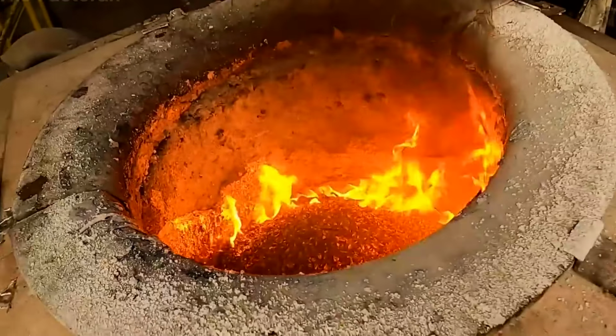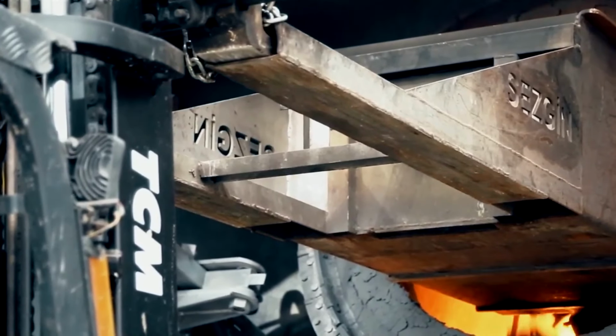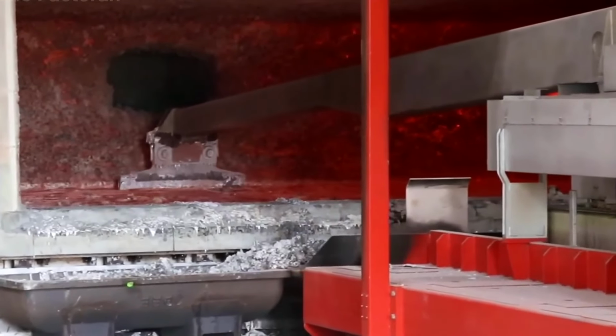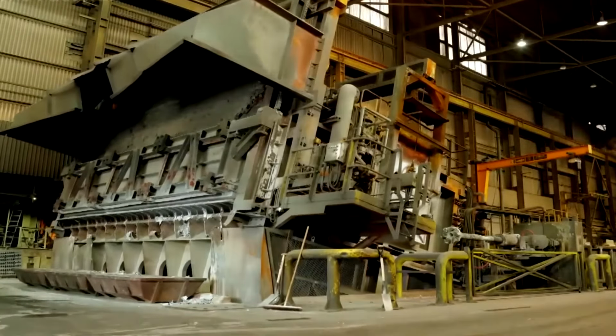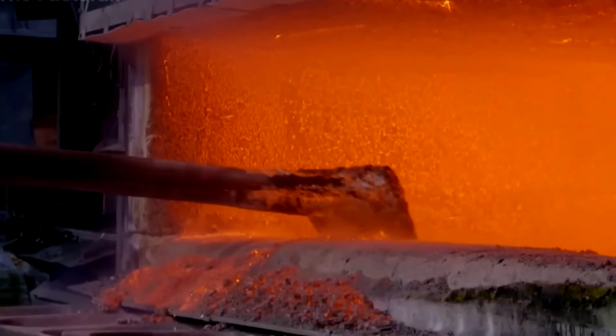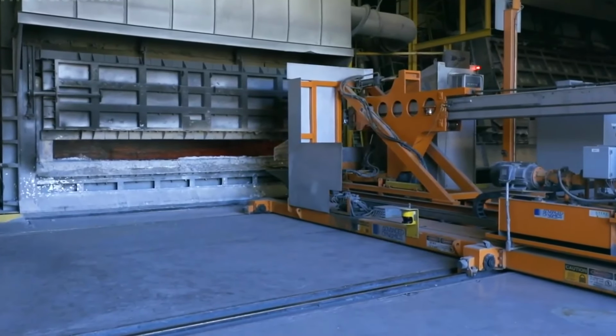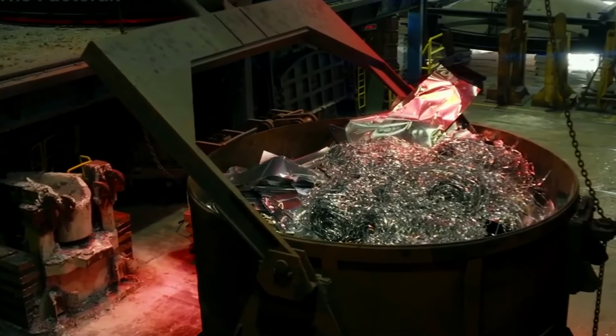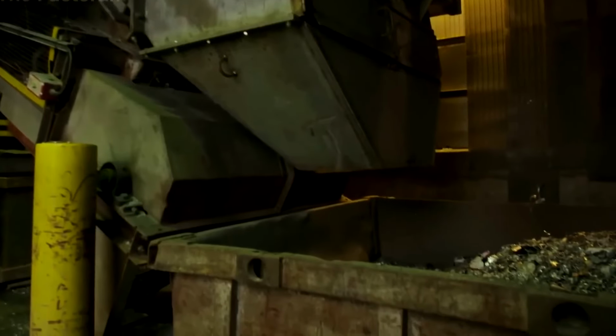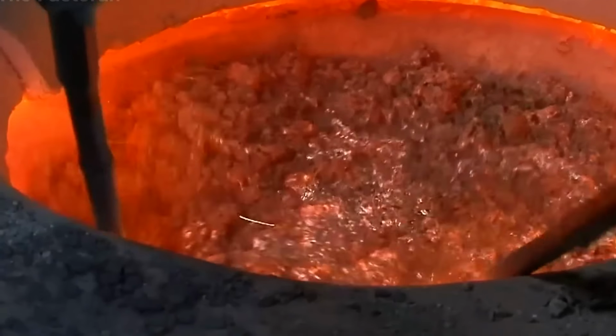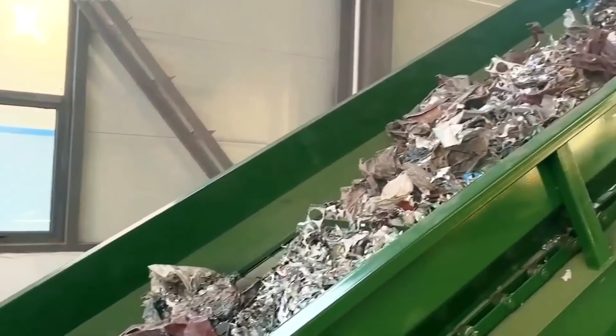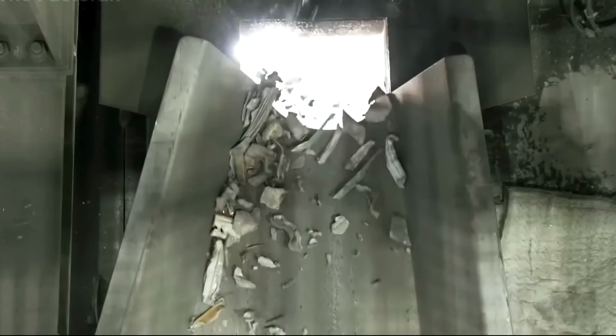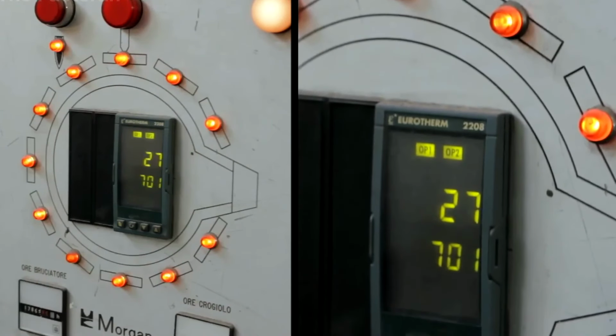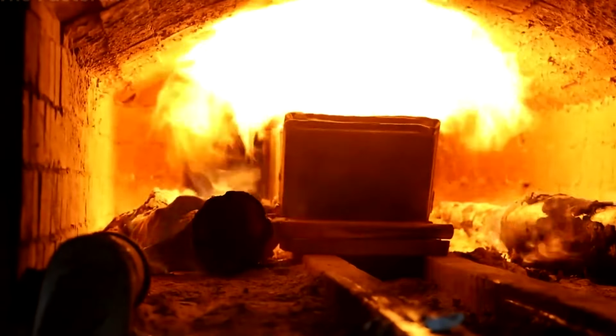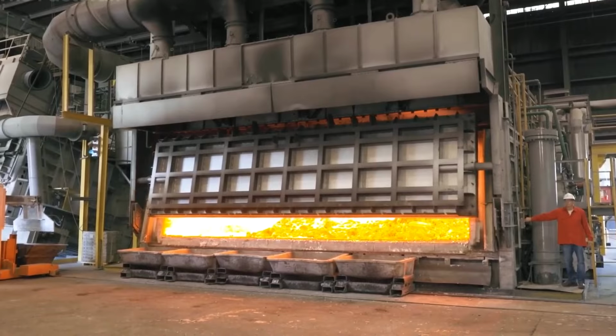Even after the aluminum has completely liquefied, it still harbors countless impurities invisible to the naked eye. These hidden contaminants include aluminum oxides, furnace dust, paint residues, and even oils left from its former life. To purge them, the plant initiates a refining process directly inside the furnace itself. The most common method involves adding a special fluxing agent to the molten bath. As the flux reacts, it binds with impurities, forming a light, foamy dross that floats to the surface. This layer is then carefully skimmed away, leaving cleaner, more refined metal behind.